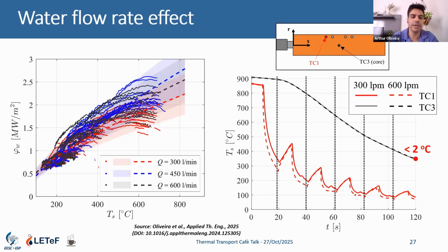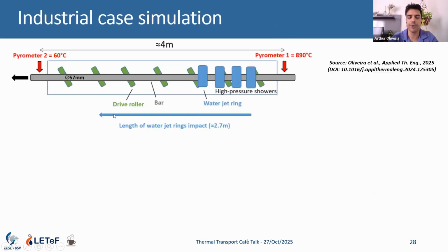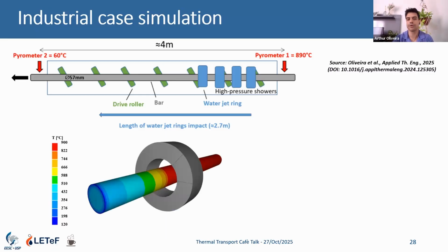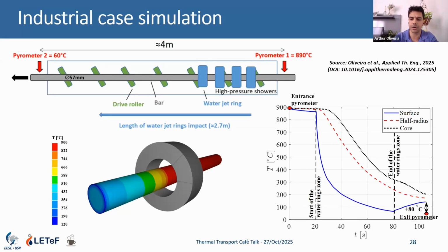And when we use the correlation we proposed for a real industrial test - here we have a real industrial line, we consider the parameters to use the correlation, we consider metallurgical effects, and considering that there is a very simple equation to put in your model - we got a sufficiently accurate result, comparing the experiment and the model. After almost 900 degrees temperature drop, we had only 80 degrees difference between the model and the experience, the simulation.